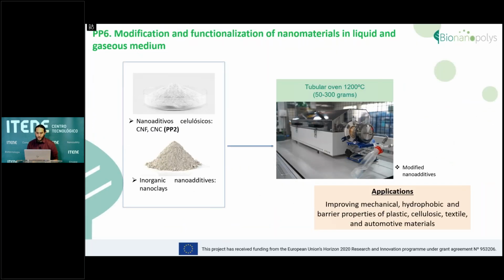We also have in pilot plant 6 solid gas functionalization. This is done in one of our tubular ovens that allow us to go to quite high temperatures of 1,200 degrees Celsius. And we can deposit these nanoadditives inside the tubular oven and allow a gas flow of the molecules that we will use to functionalize its surface and reduce the use of solvents.